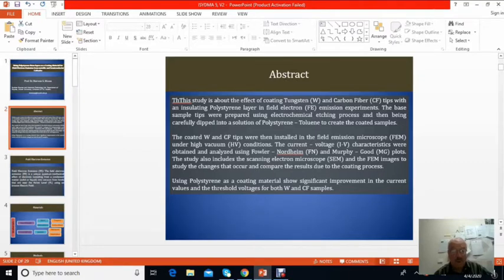Let us say that there is no known theory to cover the coating layers and the mechanism of emission. So SEM, scanning electron microscope, was used to study the profile, and the field electron microscope images were used to study the changes that occur in order to compare the two mechanisms before and after coating. We can say as an introductory result that this coating, like most of the other coatings, showed significant improvement in the electron emission current values that needed lower applied voltages for both types of composite materials.